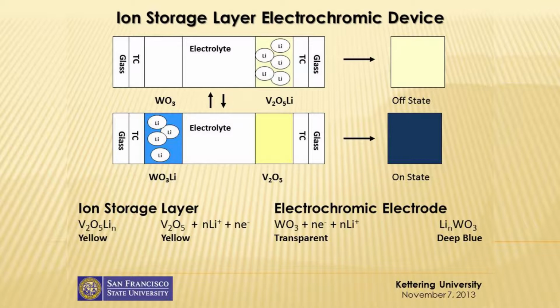It initially has a slightly yellowish color, as you see here, and the tungsten oxide is transparent. When the lithium ions move from the electrolyte to the tungsten oxide, the material becomes colored, dark blue. If you change the polarity, then all the mobile lithium ions will move back to the electrolyte, and the device will be bleached. So this is the bleached state. Off state means bleached state, and on state means the colored state. Those are the reactions that take place in the ion storage layer and electrochromic layer.